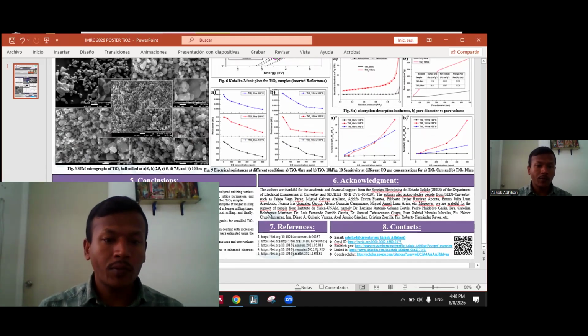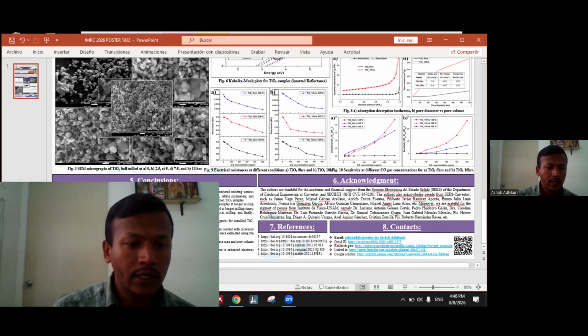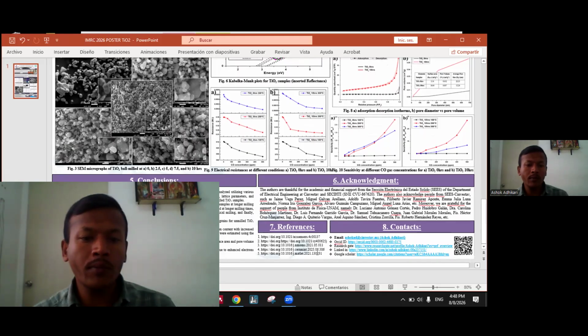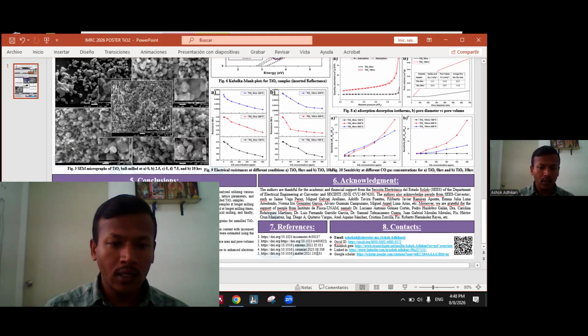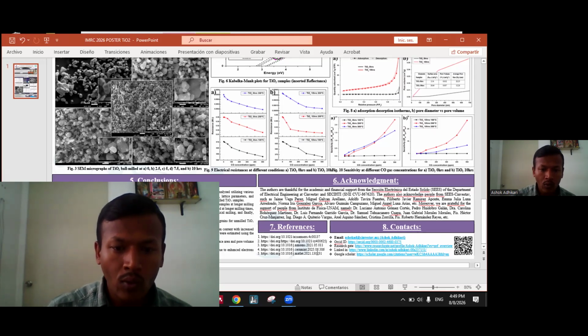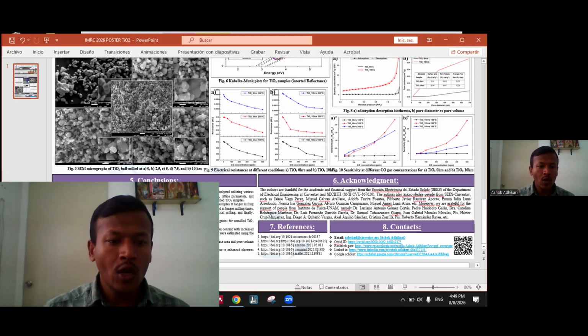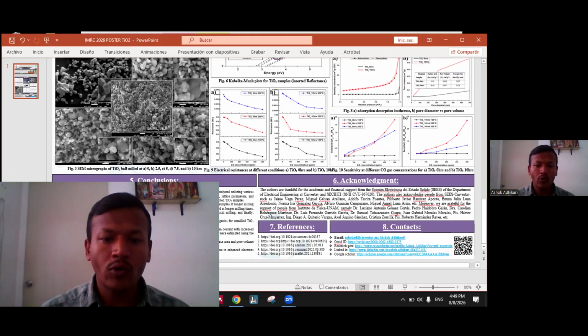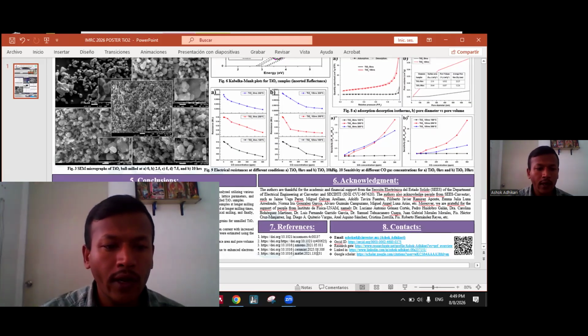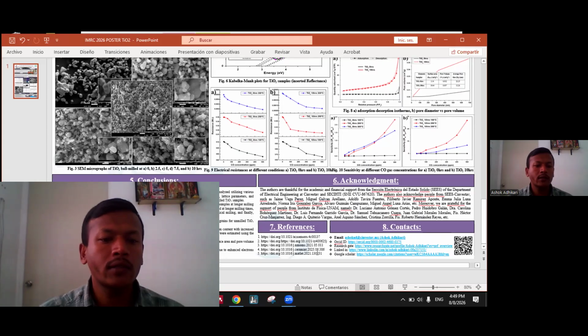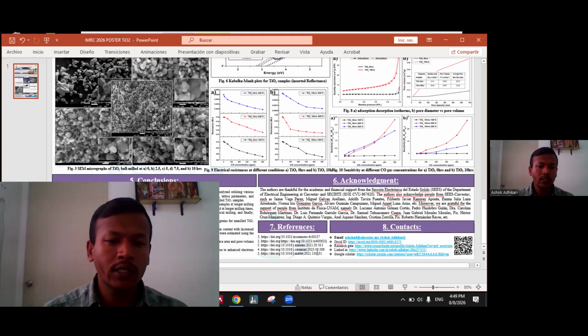Raman spectra further support XRD results, indicating the formation of additional structural defects in the TiO2 samples at longer milling times. From FTIR spectra of TiO2 samples, an increase in the intensity of Ti-O related vibrational bands was observed at longer milling times, which may be associated with structural rearrangement and increased surface exposure of Ti-O bonds. Mechanical milling finally reduces the crystallinity and particle size by generating thermal stress and cracking.